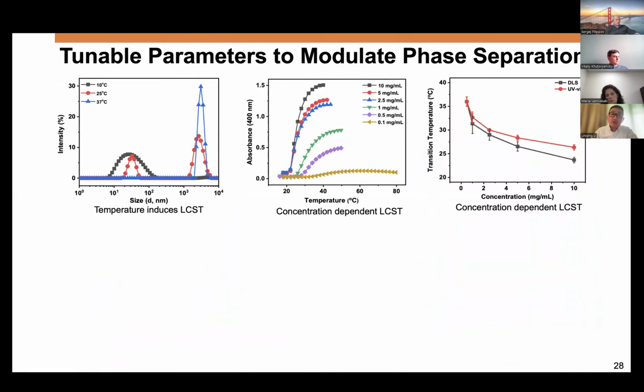Now we're using a variety of different techniques to quantitatively analyze it. Here is dynamic light scattering, showing that at 10 degrees you only see a broad peak at the smaller size. When you increase the temperature to 25, you start to see a splitting into two peaks, with larger particles forming in the solution. Then at 37, essentially all the small peaks have disappeared, showing the large peak in the large particle area.